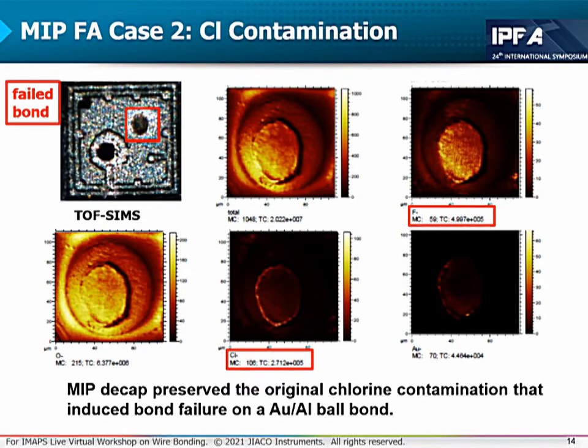In this case study, multiple SOT samples from the same batch showed electrical failure. The device has 2 dies and 4 ball bonds in total, and the bonds are gold-aluminum. Several failed samples were decapsulated by acid, and it was found that a bond lift was always present at one exact location, while the other 3 bonds were intact. EDX was performed on this lifted bond, and it showed a growth of intermetallic compound. However, after acid decapsulation, it is not possible to determine the root cause of the IMC growth.